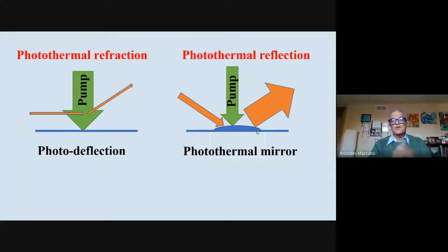You can have a photothermal reflection. It means that you create some changes in the reflection capabilities of your media, and using a pump laser, because of the heating, for example, you can make some distortion of the sample, creating some kind of bump over the surface, and then that bump will reflect the light differently, and you can see these effects in the far field.